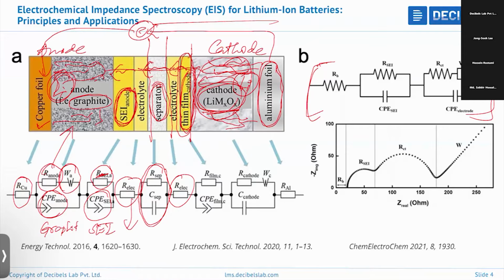But in liquid, we don't have any capacitive behavior because there is no charge accumulation. And in the separator, because the separator is a thin film, we can expect there is a storage of lithium ions at some particular time. Therefore, we can expect some capacitive behavior with respect to the separator too.